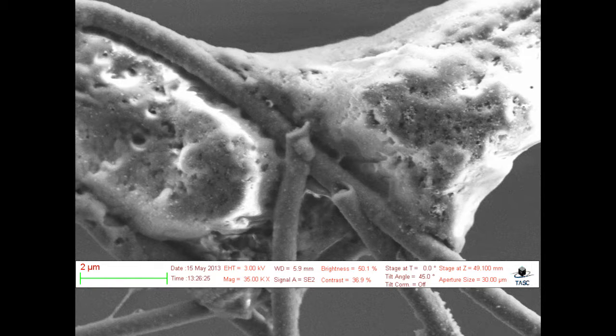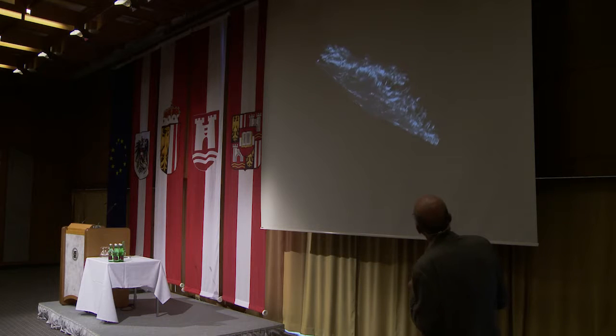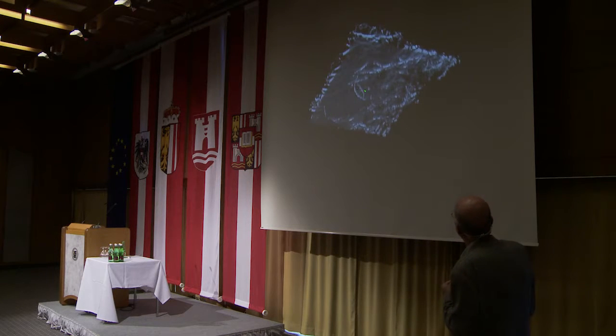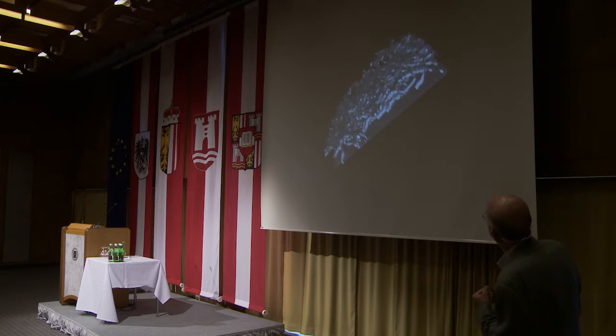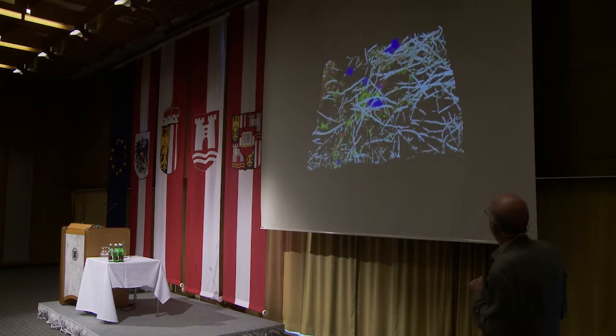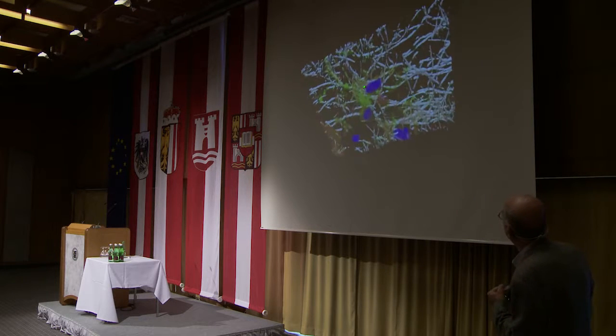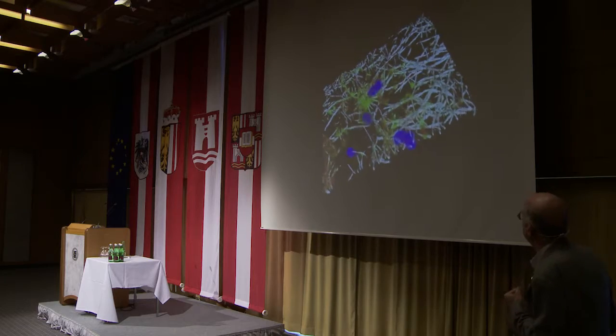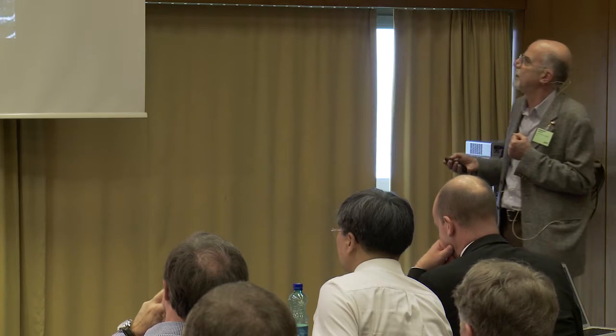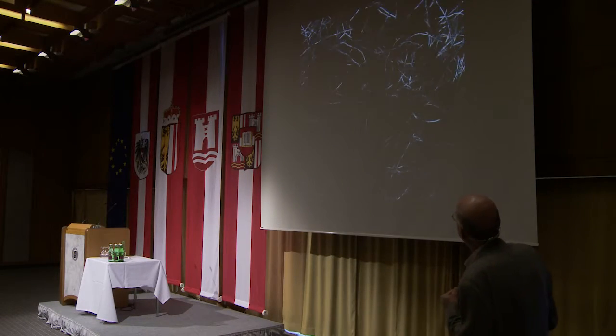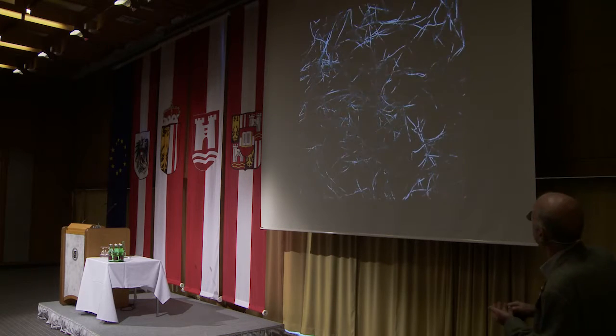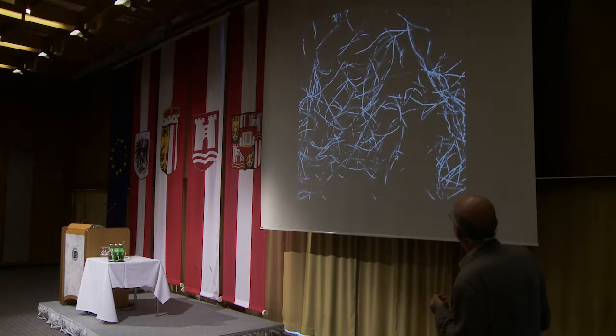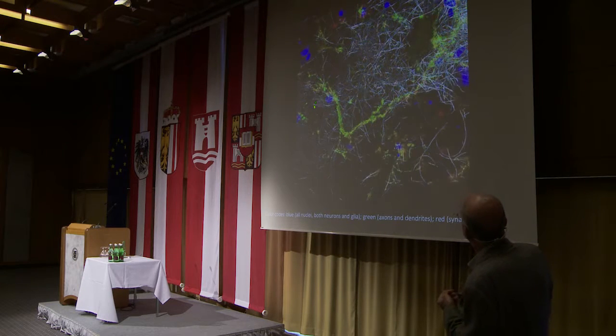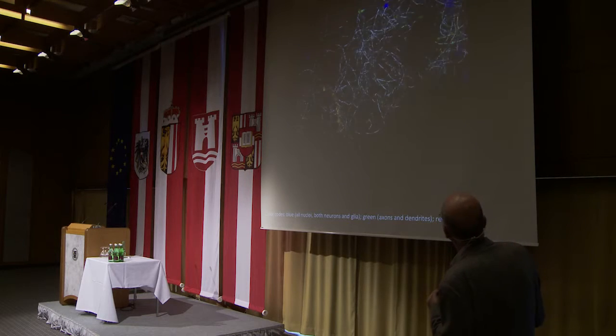So now, if we do a three-dimensional reconstruction of the sponge, this is the glass where the sponge is attached, and these are the nanotubes. This is the empty sponge, and this is the sponge filled with neurons. And so we can see that the neurons grow in 3 dimensions, and they grow very well. So also this material is a very permissive material for the growth of neurons. And here we can see the superimposition of several planes going from top to bottom. And when we place neurons, we can see that the neurons really grow very efficiently in 3 dimensions.